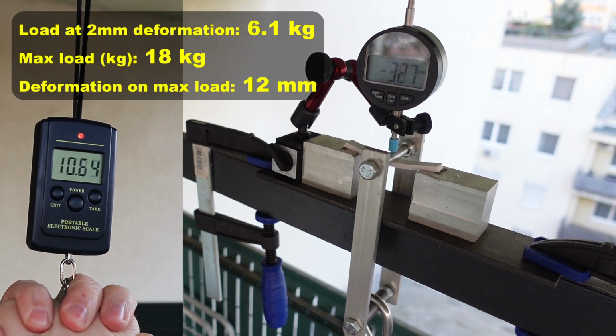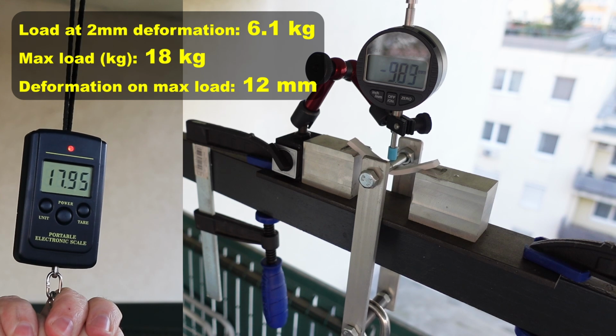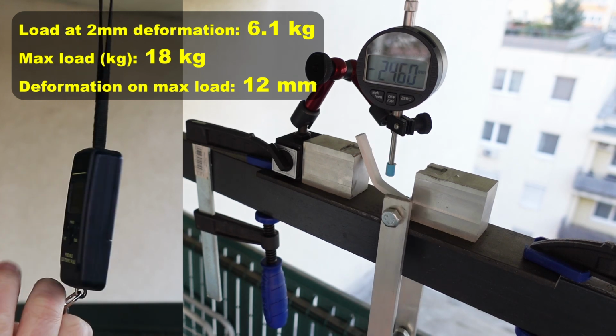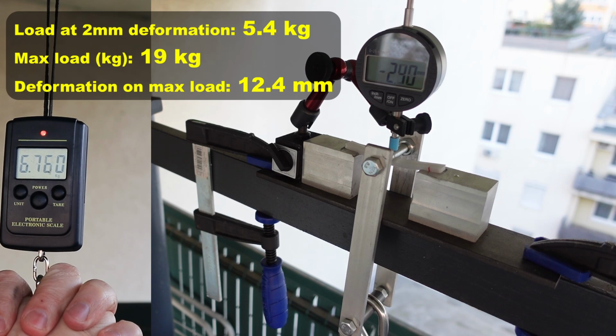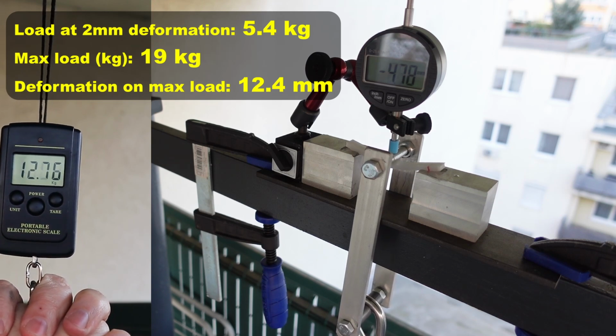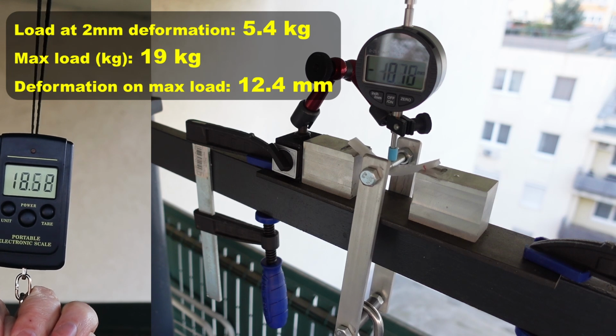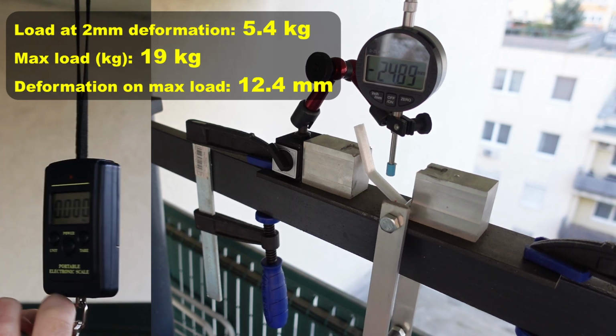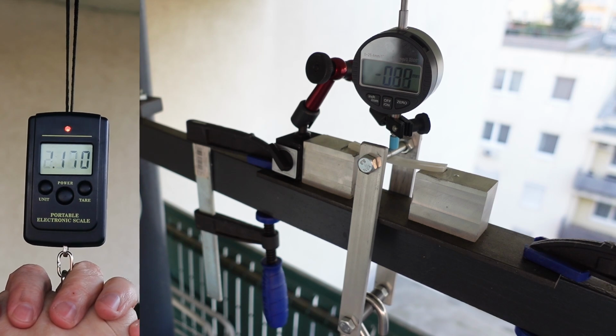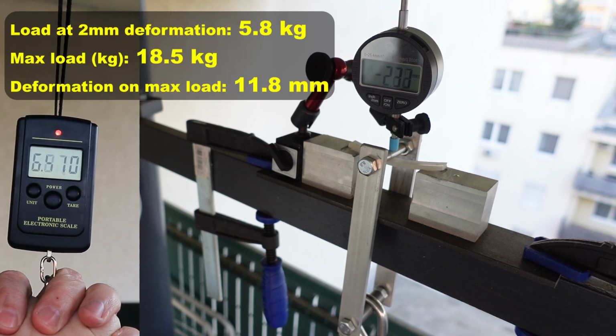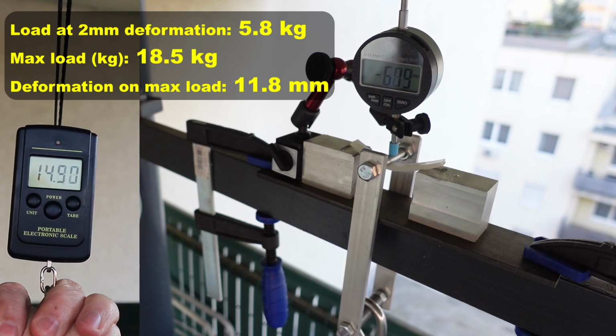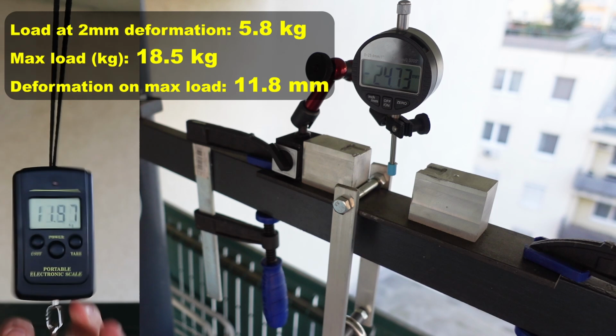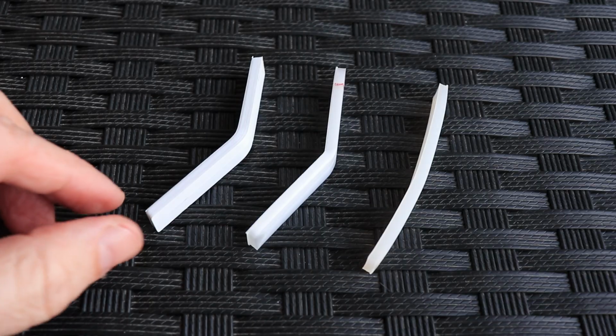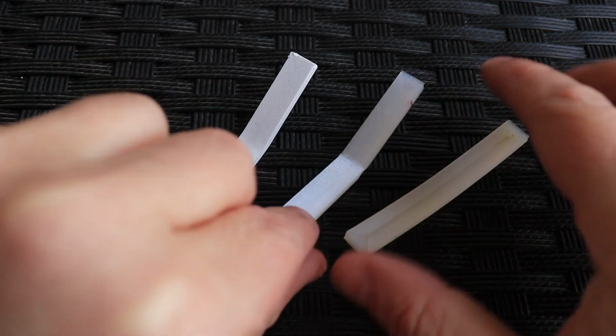And the next experiment is the bending test based on ISO 178. And I'm recording the load at 2 mm deformation, maximal load and deformation at the maximal load. ABS, they didn't break. Next one is the polycarbonate. Distance between supports is 50 mm. And you will see from the numbers very similar results to the ABS. And the next one was the nylon. And actually in this test it acts very similar to ABS and polycarbonate. And as you can see, none of the test specimens broke, so they just deform.